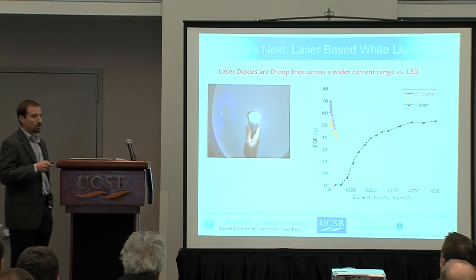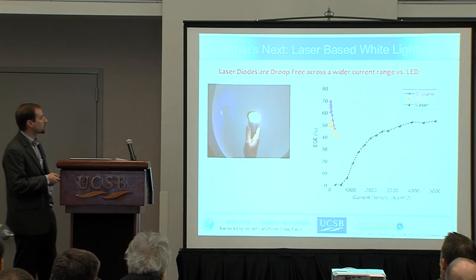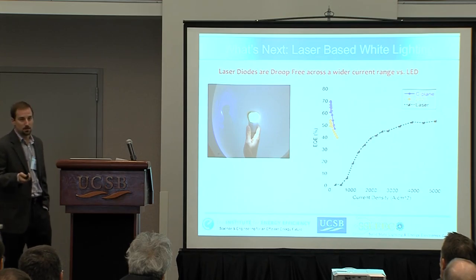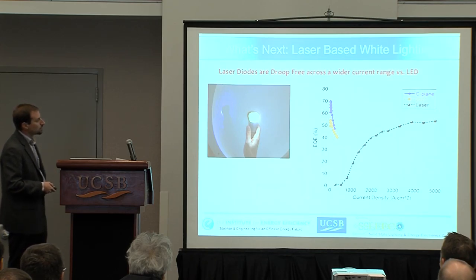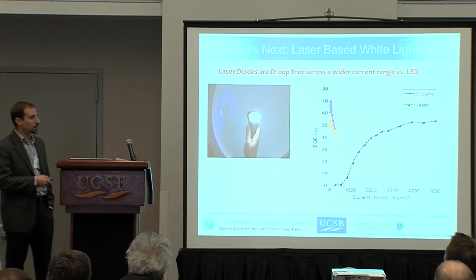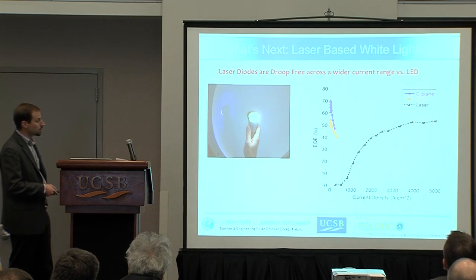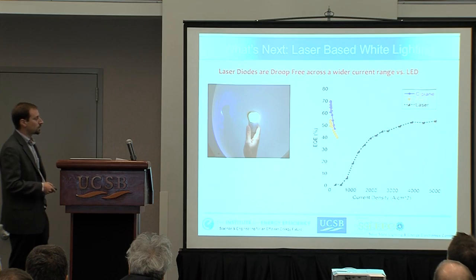What we're most excited about is what we're calling the third generation of light-emitting devices, looking at lasers as a potential pump source instead of LEDs. Why is this interesting? LEDs become more inefficient as you drive them harder, but with lasers, as soon as you hit threshold and lasing begins, your carrier concentration clamps — and what that means is your Auger non-radiative recombination clamps. So as you drive a laser harder and harder in terms of current density, you become more and more efficient, reaching EQE parity with LEDs at much, much higher current densities.